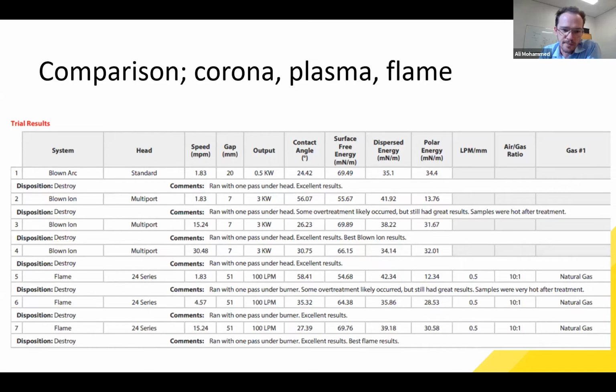We had our pultrusion treated with corona, plasma, and with flame by a third-party company. And here's just a brief overview of those results. In the center, you can see the contact angle measured with the three different types. And as a general comment, we saw good results, a good reduction in that contact angle, meaning that the surface was a high surface energy with all three types. Obviously, it'll depend on your composite, on your resin, on your chemistry, all that sort of stuff. But you can typically calibrate the line speed, the gap between the corona or plasma applicator head or the flame, and the power output to achieve a pretty good result from the raw surface. So that was our experience, and all three gave a reduction in contact angle. But typically at the moment we've preferred to use flame for our processes.